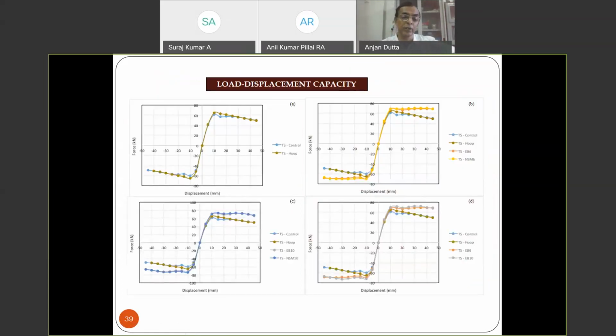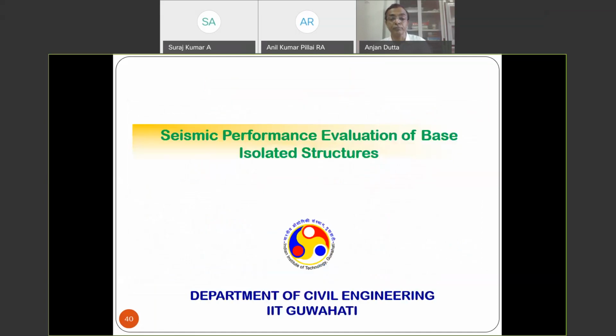So these are some of the results from numerical simulation, and you can see that there is certain enhancement in the load carrying capacity as well as the rate. See, if it is falling like this, obviously they are degrading. And if it is much flatter, obviously the degradation is much lesser. So your pre-compression as well as the confinement effect which you are getting because of the hoop, they are all coming to our advantage. Right. So this is what we have done so far at the element level and also the global level.